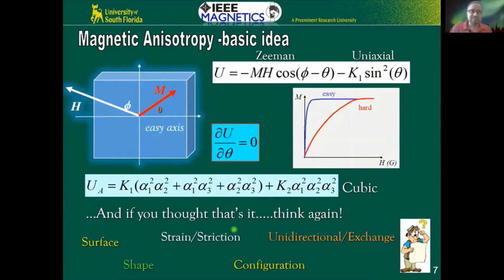Strain is important. You can actually use, for example, in thin films, if it's a magnetic film, the magnetic properties are determined by the interfacial strain. This is the elastic contribution, magnetoelastic contribution, and you can use the mismatch in the lattice and the strain to be able to control the magnetic properties. So strain can play a role too. Configuration is something interesting. I'll come to that towards the end.